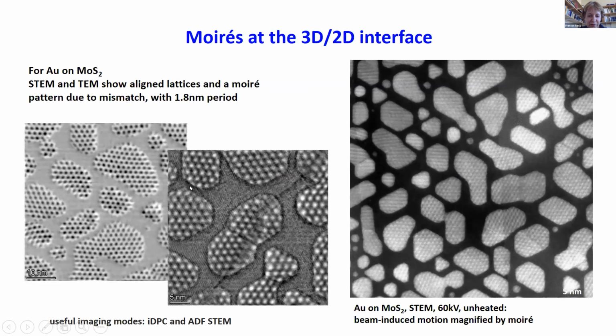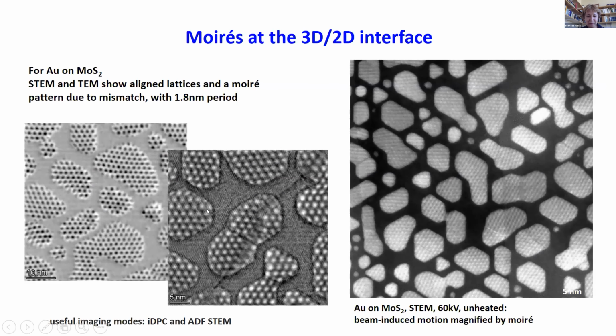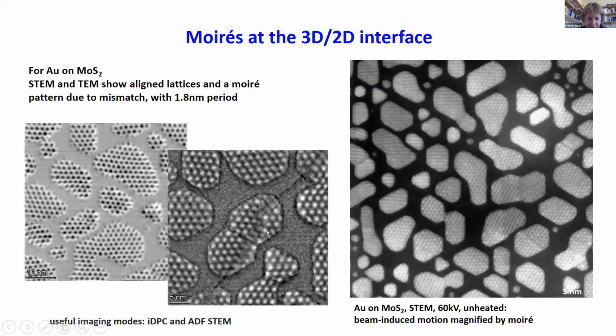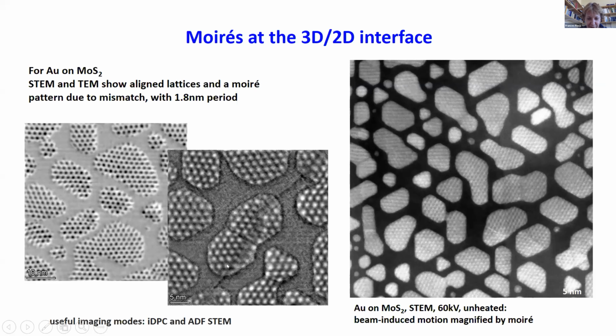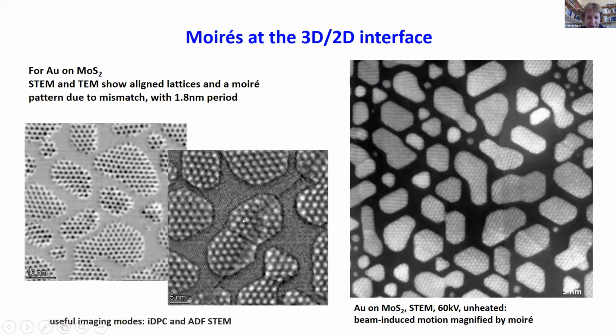And so these are actually ex situ images of gold on MoS2. You can see the MoS2 structure in between. You can see the shape of the gold islands. And what you can see most strikingly is a moiré pattern that reflects the difference in the repeat distance between the gold and the MoS2.